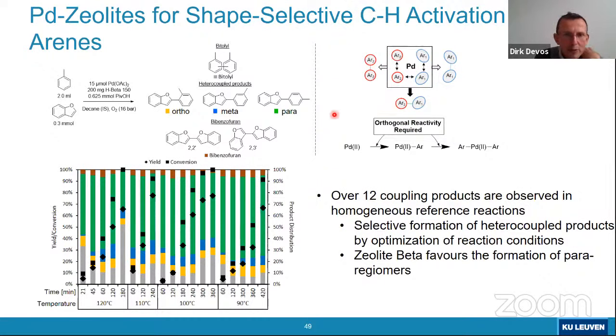To some extent, we have already been quite successful in shaping this system up to a system that can successfully do heterocouplings also, for instance, of benzofuran and toluene. That's a case which so far works quite nicely, in which we see all these concepts of not only shape selectivity, but also selective formation of the heterocoupled product come back. We need to modify the system. For instance, now Yannick adds pivalic acid as an additive rather than acetic acid.